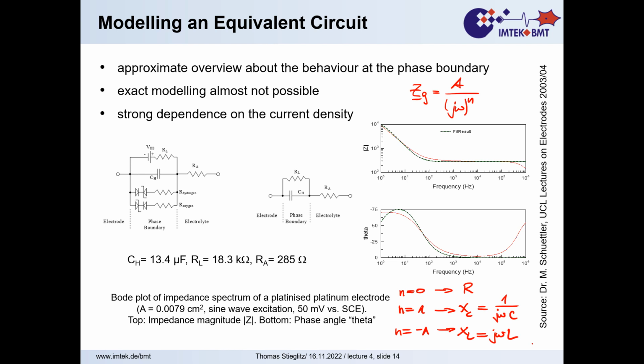And that guy found out that if n is equal to 0.5, you get something where you have a real part and an imaginary part, and the real part is dependent on the frequency. That means a resistor that depends on the frequency. That's really weird because a resistor should be independent of frequency. And this is something you can imagine, that there are diffusion processes at the surface, and at a particular roughness, this hinders the charge to go over the surface.